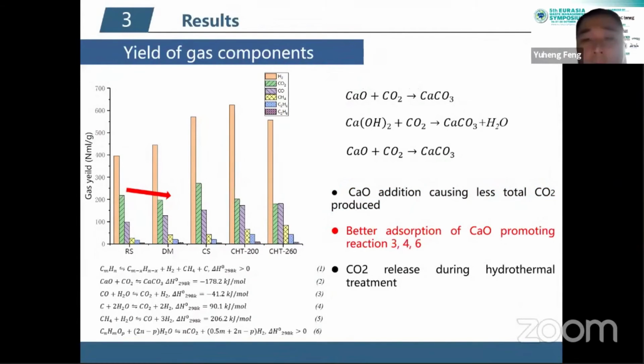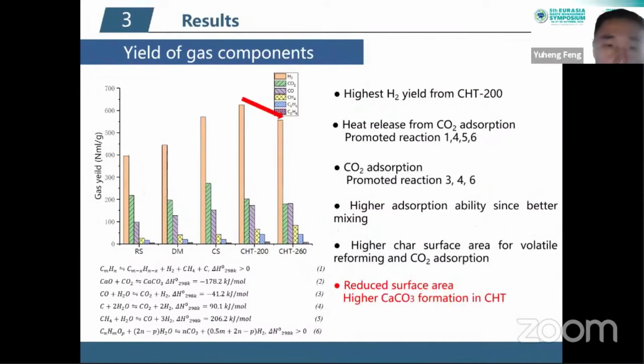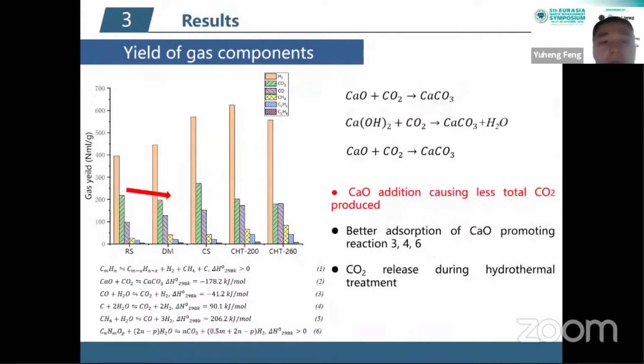And for carbon dioxide, we found that for the dried mixed samples, the carbon dioxide is reduced. This is because the calcium oxide addition causes less total carbon dioxide to be produced.